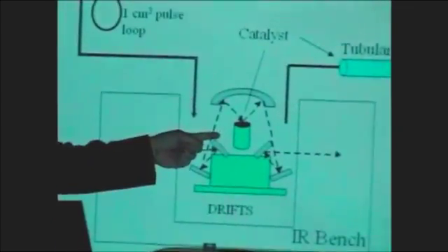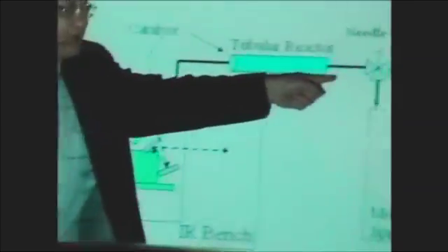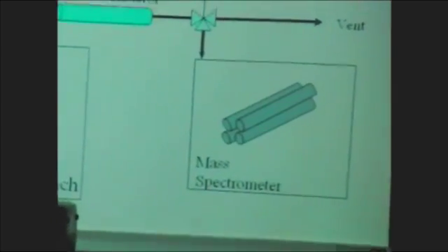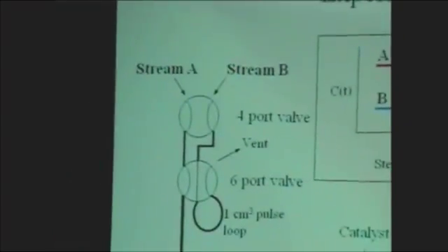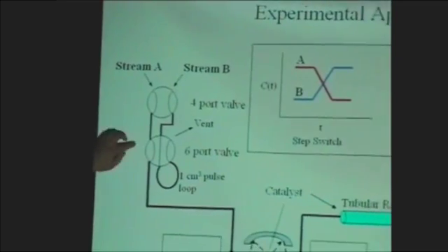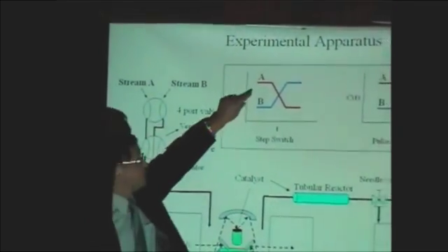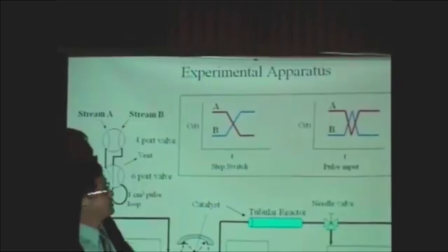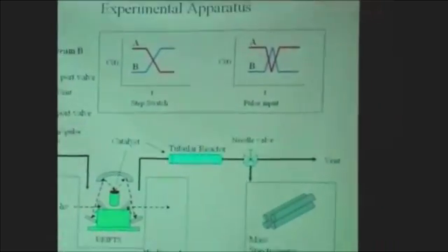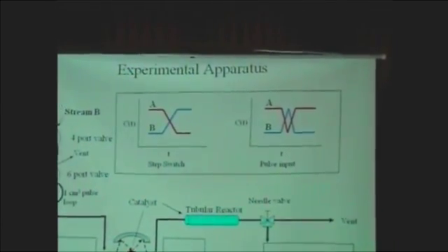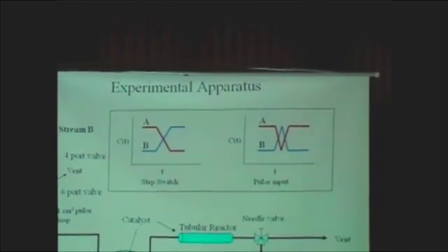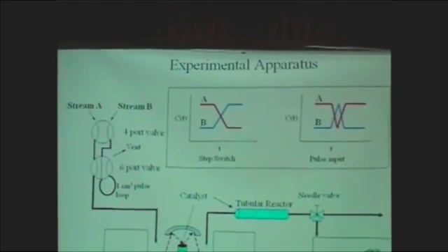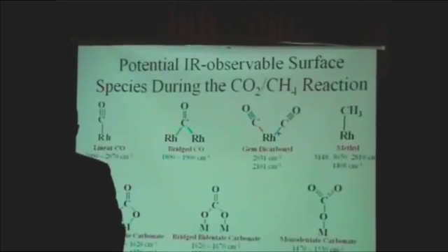So the key in this technique is using infrared to look at what species adsorb on the catalytic surface, and using the mass spectrometer to monitor the products. We also have a number of valves here to introduce changes in the reactant concentration. For example, we use a 4-port valve to make a step switch from one stream to another. We can also use a 6-port valve to make a pulse change in the reactant concentration. And we can vary the pulse loop to decide what amount of species we introduce.